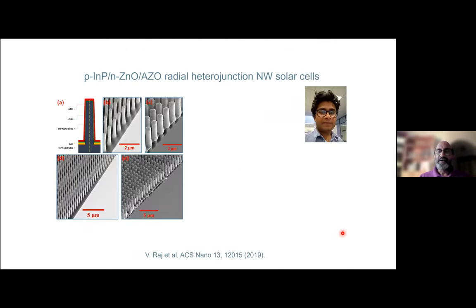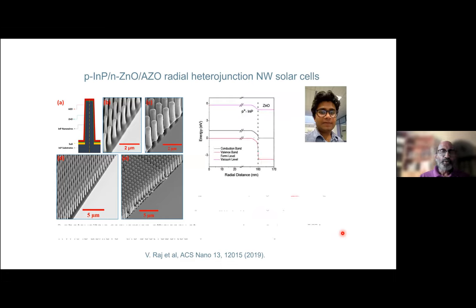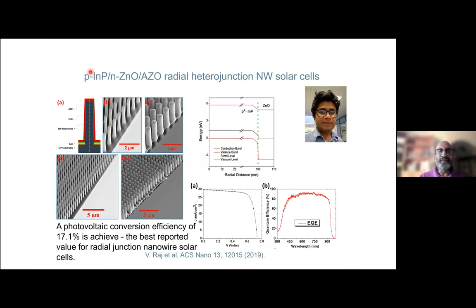And this is the work of my former student, Dr. Vidur Raj, who is now at Glasgow University as a postdoctoral fellow. What he has done is grow these P-type indium phosphide nanowires, and then coat them using N-type zinc oxide, using atomic layer deposition. That means you can get a beautiful conformal coating of these, and finish off with aluminum zinc oxide to have better contacts, for example. These are the so-called core-shell structures which I was talking about.